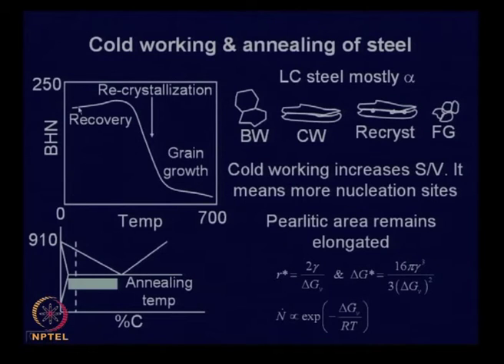In the recovery stage, there may be a little increase in hardness; this is strain aging. Sometimes the solute atoms, particularly interstitial carbon and nitrogen, can precipitate and block the dislocations, and this can increase the strength a little, but it helps in removing the residual stresses and micro stresses through rearrangement of dislocations. And after a certain temperature, there is a rapid drop in strength. Here new recrystallized grains are formed, and these grains are strain free, as shown over here.